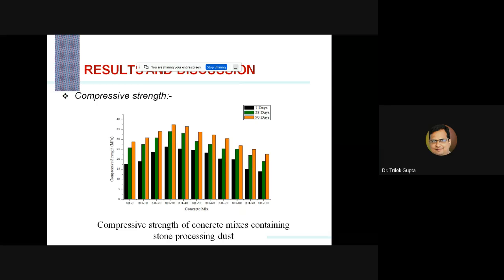Now we come to our results and discussion part. This figure shows the compressive strength of concrete containing stone processing dust up to 100% replacement. So we can observe from this figure that, let's say we take the 28 days strength, from zero it was around 26 approximately, but it goes up to approximately 33 up to the replacement of 30%.